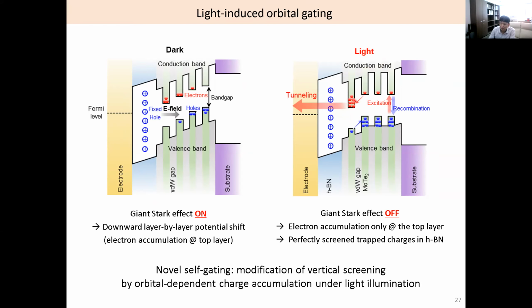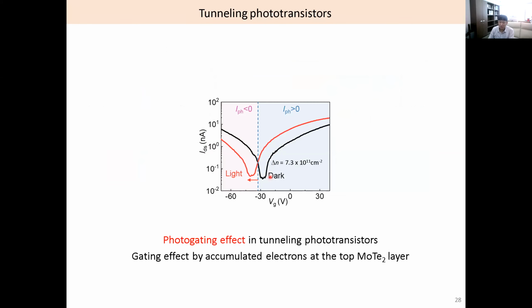But you know, tunneling current is extremely sensitive to the tunneling distance. One angstrom means 10 times lower current. So tunneling current is dominated not by the average doping concentration, but by the carrier density of the top MoTe2 layer. So we achieved this photo-gating effect. Professor, you already showed this curve in the review, but in the review, it was drawn by hand. So this is exactly the photo-gating effect without the photoconductive effect.